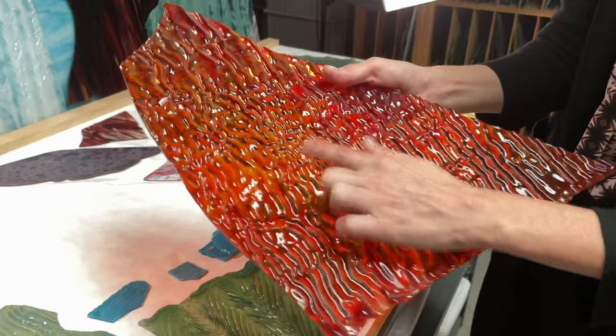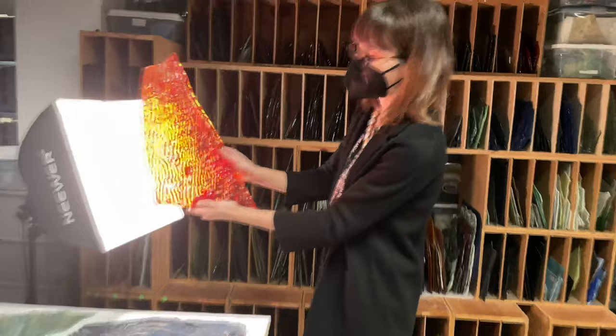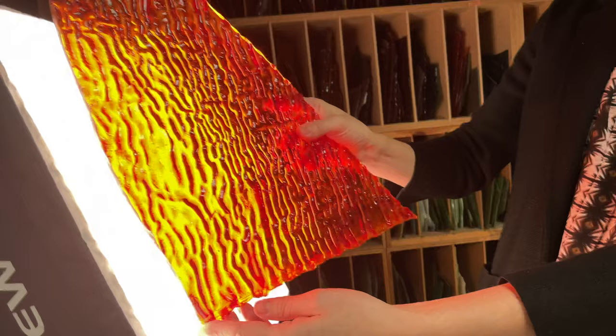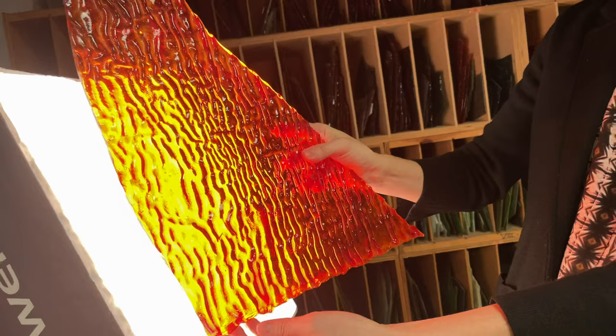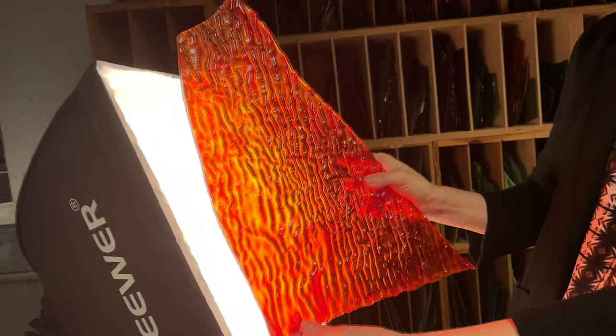One of Tiffany's superintendents of his glass furnaces out in Corona, Queens, described the manufacturing process. And he said that the rolling table was actually on wheels on a track, and it was moving. And then the roller that was rolling the sheet of glass flat was moving at a different rate. So the result was to jostle the glass in these very irregular ways and create an artistic type of ripple. And this would be used in all manner of ways.